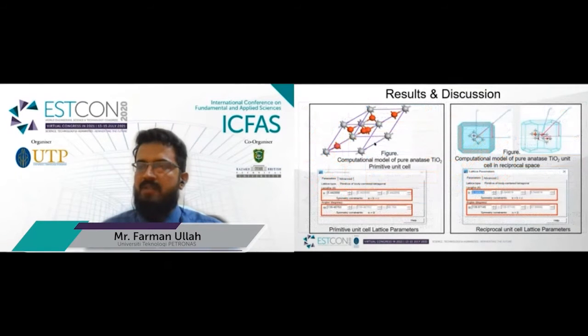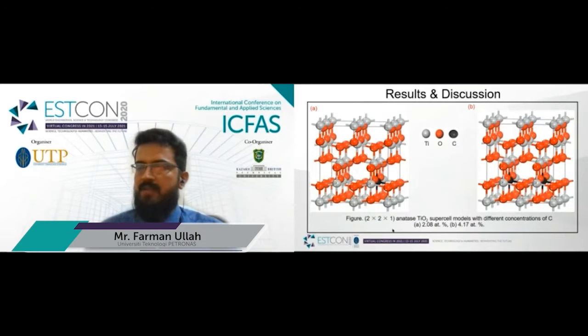On the left-hand side in this figure, a computational model of the pure anatase TiO2 primitive unit cell is shown along with optimized lattice parameters, and on the right-hand side, the figure includes the computational model of the pure anatase TiO2 unit cell in reciprocal space. These are the computational models for the 2x2x1 anatase TiO2 supercell with 2.08 atomic percent of carbon doping, and figure B is for 4.17 atomic percent concentration.